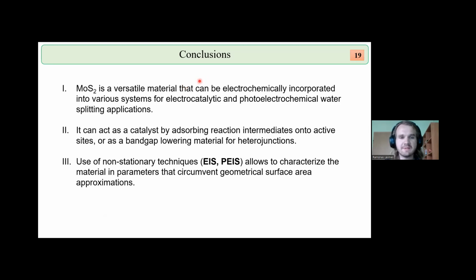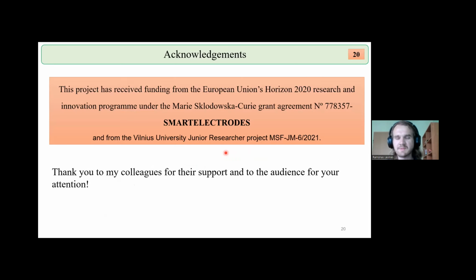So overall, molybdenum sulfide is really a versatile material. It can be used as an electrocatalyst by itself due to its properties. It can also be used as a semiconductor of a lower band gap, and it could be used to form heterojunctions with other materials that have larger band gaps, and thus create a more photocatalytically or photoelectrochemically active composite. And especially electrochemical impedance spectroscopy and photoelectrochemical impedance spectroscopy allow us to circumvent the calculations of geometrically active surface area, or specific surface area, and obtain operating parameters that are perhaps more directly comparable, at least for the samples that had been measured under similar parameters.